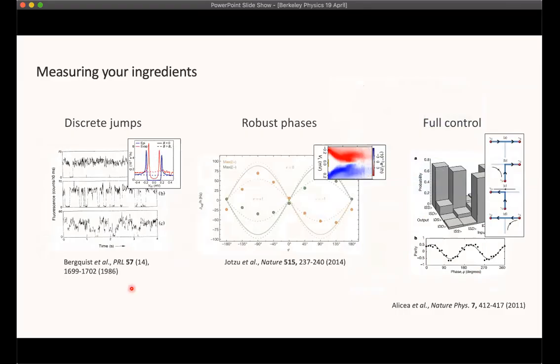So let me just recap now. I hope that I've shown you that the discrete jumps that tell us that we have some of the ingredients necessary for building our quantum state are things like the induced superconductivity that we have to check and tweak up and improve in our materials. And we seek robust phases for building quantum systems, and a really compelling piece of evidence for a robust phase, the topological phase, is this observation of a gapless boundary followed by the presence of experimental evidence for Majorana quasiparticles like zero bias peaks. And finally, looking forward, having established this robust phase, we expect to be able to demonstrate control of these systems by performing either braiding or projective measurements to show that we can manipulate the Majoranas for building quantum computers.